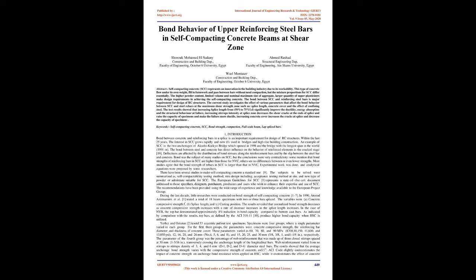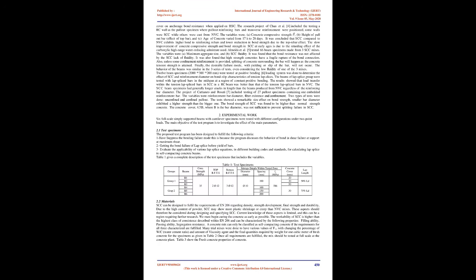The bond between steel and concrete has direct influence on the behavior of reinforced elements in the cracked stage. Deflections are affected by the distribution of bond stresses along the reinforcement bars and by the slip between the steel bar and concrete. Bond was the subject of many studies on SCC, but the conclusions were very contradictory. Some mention that bond strengths of reinforcing bars in SCC are higher than those for NVC, others see no differences or even lower strengths.